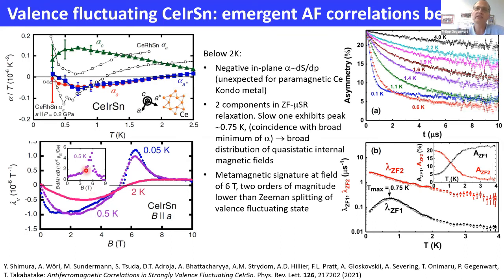Because a negative sign in cerium systems we typically only have within a magnetically ordered regime. You know, the sign of the thermal expansion is related via the Grüneisen relation with the pressure dependence of the characteristic energy scale. And typically for paramagnetic heavy fermions, the sign of alpha is always positive because the Kondo scale is getting enhanced with pressure, and Kondo scale is the dominating scale. So only if we are in a magnetic regime where the ratio of RKKY to T_K dominates, only then the sign of thermal expansion could become negative. And that this happens in an intermediate valence system below 2 Kelvin, while the valence fluctuation temperature is about 500 Kelvin, this really came as a surprise to us.